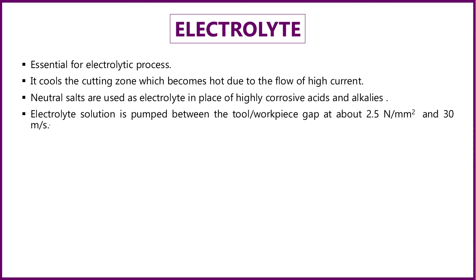Then the electrolyte. It is essential for this process, and it cools the cutting zone, which becomes hot due to the flow of high current. Neutral salts are also used as an electrolyte in place of highly corrosive acids and alkalines. Electrolyte solution is pumped through the tool and workpiece gap at about 2.5 Newton per mm square and 30 meter per second.